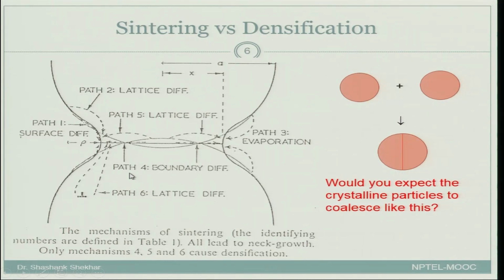Mechanism 4 is grain boundary diffusion. Basically the material is diffusing into the neck region by the grain boundary mechanism. In path 5, lattice diffusion, from somewhere over the center, the material is going to the neck region, and in path 6 you have lattice diffusion from the center to somewhere in the neck region, where the material is flowing. Some of these mechanisms, like I said, will lead to densification, and the densification we are talking about is the center to center distance.